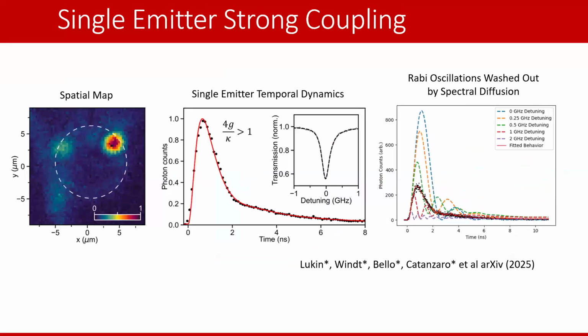And so you can see that here, by tuning the cavity with the gas tuning line, we can tune it to a regime where there's only a single defect strongly coupled to the cavity. But again, because of spectral diffusion, the time trace of this strongly coupled defect to the cavity mode doesn't show the expected Rabi oscillations. If you're in any strongly coupled system, you should expect to see Rabi oscillations in population between your two modes.